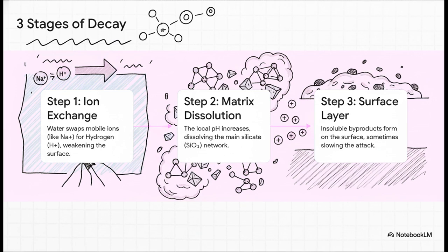First up is ion exchange. Think of it like a bad trade. The glass has these weakly held sodium ions, and water comes along and swaps them for hydrogen ions. This trade-off weakens the whole structure right at the surface. Then, with those ions gone, the local pH right there on the surface changes, and that change starts to dissolve the strong silica backbone of the glass itself. And finally, some of that dissolved material can actually precipitate back onto the surface, creating a new layer that, if you're lucky, might slow down any more damage.